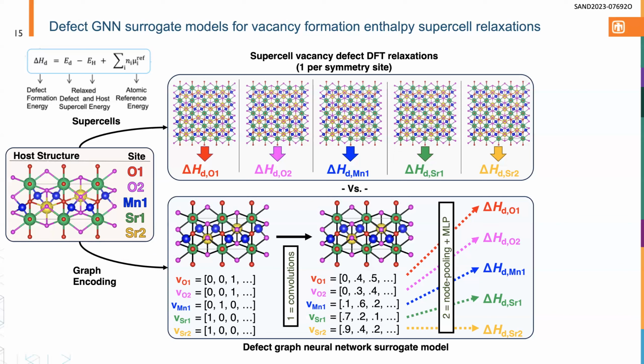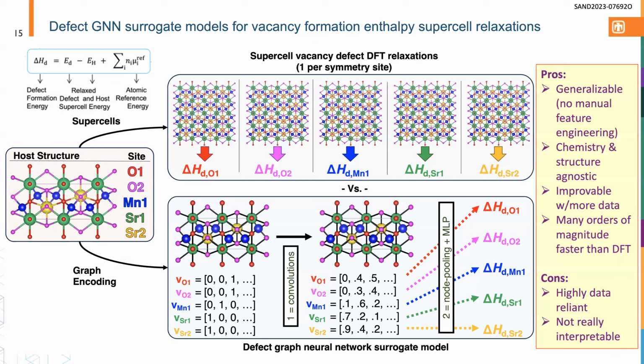And then at the end of your convolutions, instead of doing a pooling where you basically sum all the information together across each individual feature vector, you just pluck out that particular feature vector associated with each atom in the crystal structure. So it's called node pooling. And then you run those through any kind of final feed forward layer to directly predict the vacancy formation energies for each site in the crystal structure.